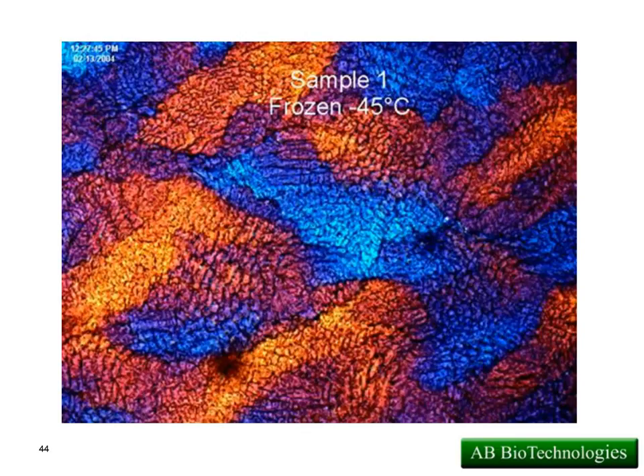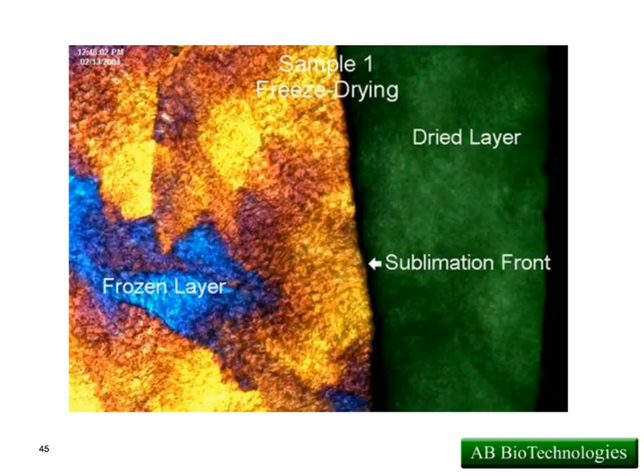So then we start freeze-drying the sample, collect an image in the frozen state, then we start freeze-drying. Now we freeze-dry at a temperature well below our glass transition or eutectic melting temperature that we've determined in the DSC. I want to get an image of an intact dried layer. So what we see on the right is the dried layer, the left is the frozen layer, and that line in between the two, that razor-thin line, is what we call the sublimation front. That's where we're actively converting ice crystals to vapor.